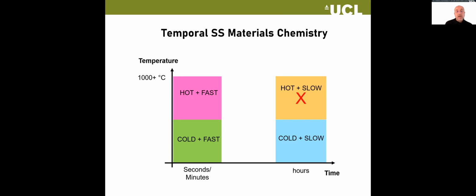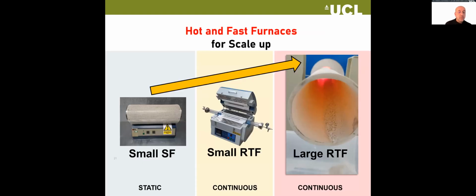So I call this temporal solid state materials chemistry, and every material is different. The other innovation that I think our group is, I wouldn't say unique, but there aren't many groups that I know doing this. And that is in the use of, not only do we use continuous reactors to make initial precipitates, we're also now looking at how we can rapidly look at sort of flash heating. So the first thing is the static furnace. This is a small tube furnace in which we introduce samples and take them out again. So we call this static flash heating, okay? Because the furnace stays still, the sample goes in, it comes out. We have a procedure for that. And of course, you can vary the time and the temperature.